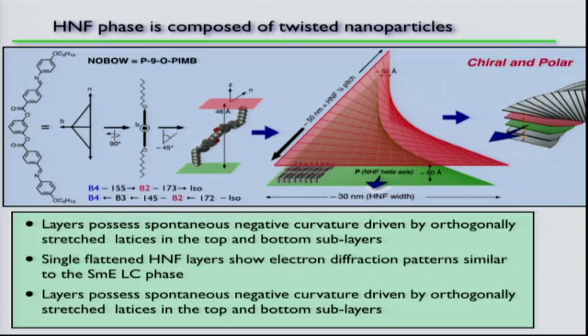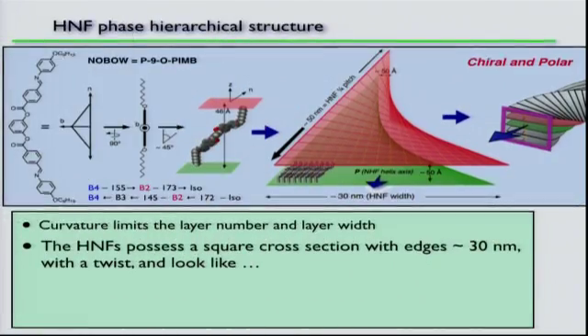I don't have time to go through the details, but Noel worked out the basic structure of the B4 helical nanofilament phase, thinking of it as a kind of smectic liquid crystal phase where you've got these orthogonal rectangular lattices in the top and bottom half layers that cause a spontaneous Gaussian curvature. You end up with this twisted layer structure, and because of the Gaussian curvature, the layer width and the number of layers is limited, and you end up getting these little nanofilaments that spontaneously limit to about 30 nanometers on a side. Because of this negative curvature, you end up with a square cross section.